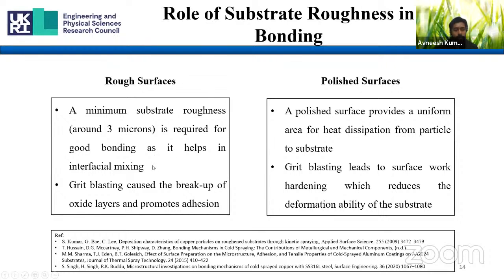However, they are also saying that we need to investigate further whether this much roughness is okay for a given coating thickness or not. Some researchers are also saying that grit blasting helps bonding, because grit blasting helps in breaking the oxide layers and promotes adhesion at the contact. Also, grit blasting creates rougher surfaces, which helps in interlocking. On the other hand, researchers are saying that a polished surface provides a uniform area for heat dissipation from particle to substrate, which further helps in thermal softening. And they say that grit blasting leads to surface work hardening, which reduces the deformation ability of the substrate and affects the bonding adversely.